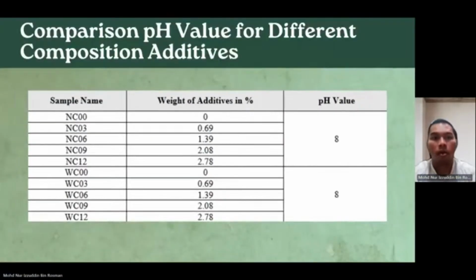Next, comparison of pH value for different compositions of additive. As we can see, every sample has a different weight of additive. NC00 doesn't have any additive, and NC03 with 3 grams of additive shows 0.69%, NC06 1.39%, NC09 2.08%, and NC12 uses 2.78%, similar to the waste cooking oil. But the result for all the samples showed the same pH value of 8. This shows that all the soap samples have similar pH properties.